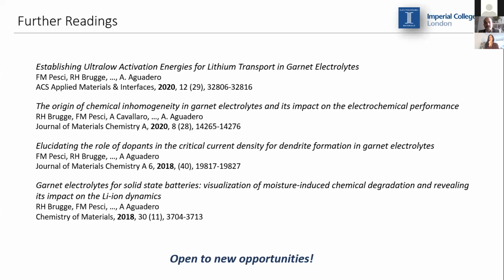No, I mean, you have to consider that we do the sintering at 1150 for 6 hours, and the etching is only 900 for 30 minutes. So it doesn't lead to a microstructure change. Yeah, I can confirm that we never see any change in microstructure.